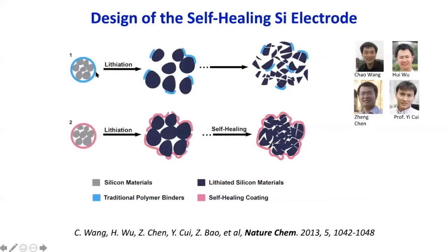It also has to have some conductivity. So we normally incorporate a little bit of carbon or carbon nanotube to make this blue part electrically conductive and ion conductive. But the problem is silicon is very rigid and brittle. So if we charge it up, then the particle will have a volume expansion. And then when you discharge, lithium will come out of the silicon, and then it will shrink. So when it expands and shrinks, just after a few cycles, the particle will break and fracture into pieces.